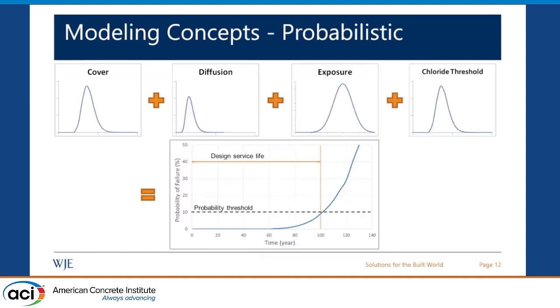And since we are performing probabilistic modeling, we describe the key input parameters with probability distributions. And our model is flexible, so we can use any probability distribution. We're not limited to normal distribution. So we often use, for example, log normal for cover distribution. We use beta distribution to define the chloride threshold for black bars, for example.